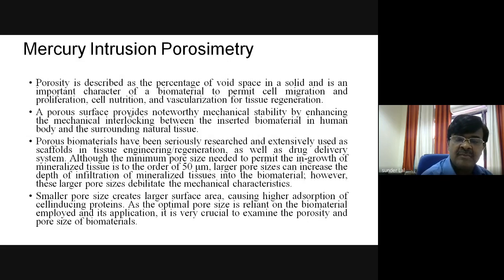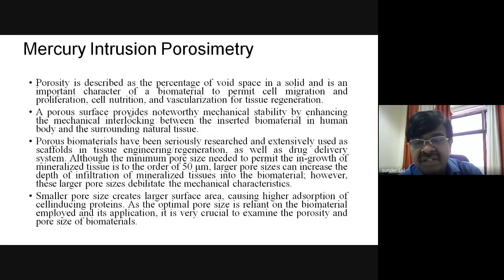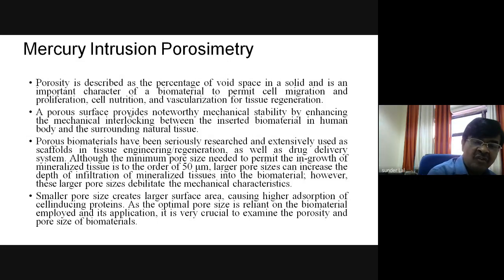So the mercury intrusion porosimetry test is very important in the case of drug delivery systems and tissue engineering. The minimum pore size needed to permit ingrowth of mineralized tissue is on the order of 50 micrometers. The larger the pore size, the more it can increase the depth of infiltration of the mineralized tissue into the biomaterial. However, these larger pore sizes compromise the mechanical characteristics.